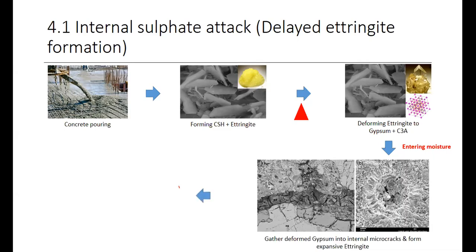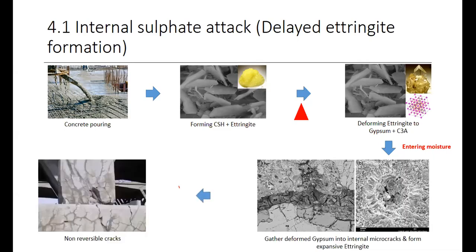This is not good, because there will be non-reversible cracks. We can't reverse that reaction back to the normal situation. I already told you there are two key things involved with this reaction. The first one is the heat. Because of that heat, the formed ettringite gets decomposed. And in the presence of moisture, the ettringite is generated back. So if we can eliminate the heat generation, the ettringite will not decompose, and there will not be a risk of DEF formation.